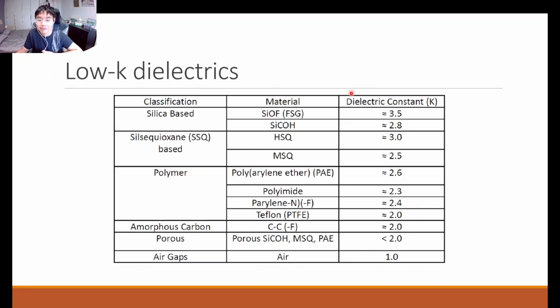So these are some examples of the low-K dielectrics that have been used or have been proposed to be used in the semiconductor materials. For example, there's a silica base, so it's trying to not deviate too much from the idea of SiO2, but maybe incorporating some fluorine. So this is your fluorosilicate glass. Incorporating some carbon groups in. So this is like kind of your organosilicate glass.